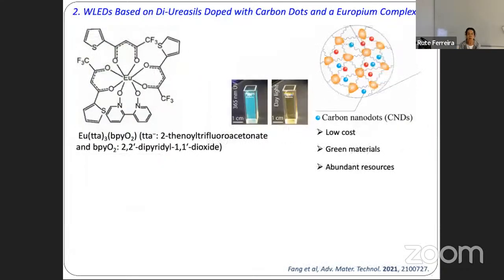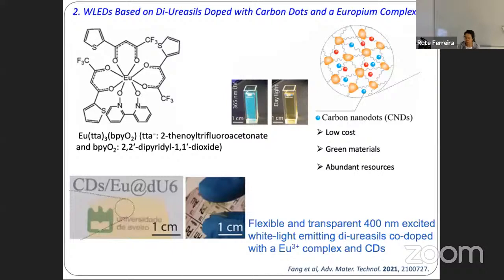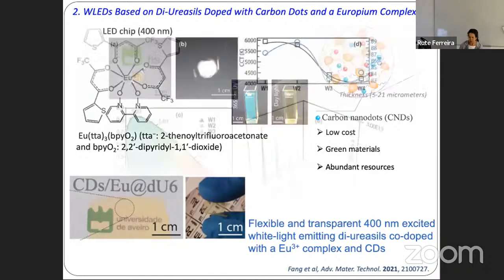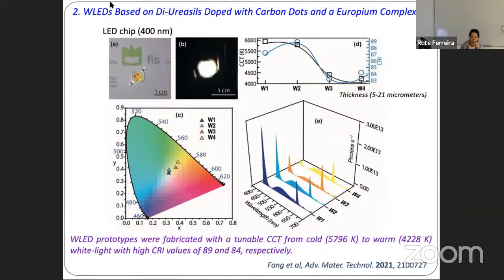Okay, featuring now again white light based on organic and inorganic hybrids, we decided to replace the terbium complex by a europium one. The idea was to provide the red component for the white light. The green and blue components were in fact provided by carbon dots that display a broad emission in the blue-green spectral regions. The rationale for the use of carbon dots is based on their low cost. They are sustainable materials from abundant resources. Their incorporation into the diureasils enables the preparation of transparent and flexible films. Once again, we deposit our material on top of a commercial LED chip, this time emitting in the blue.